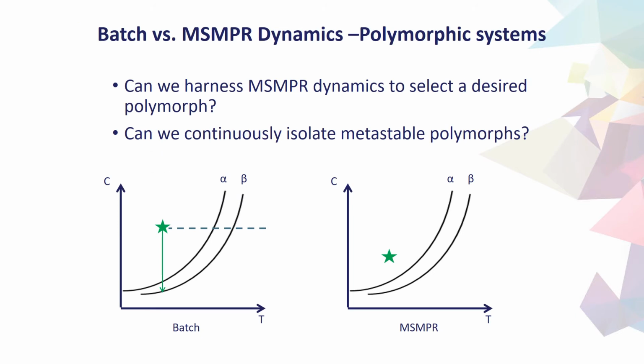Polymorphism is the ability for a compound, when crystallized, to exist with multiple crystalline phases or multiple crystal structures. So why is this important to control for the crystallization of APIs? Well, those different crystalline phases can have different solubilities in your small intestine, which thus controls the bioavailability of the drug once dosed, for example, as a tablet in an oral solid dosage form. So as a result, we have to be able to control polymorphism in continuous crystallization if we are to use continuous crystallization techniques in the isolation and crystallization of APIs.